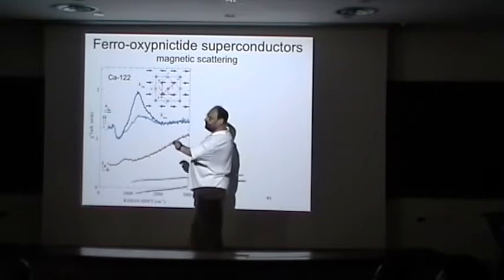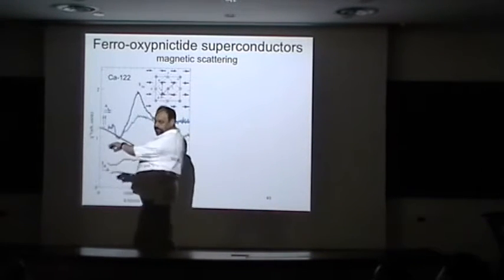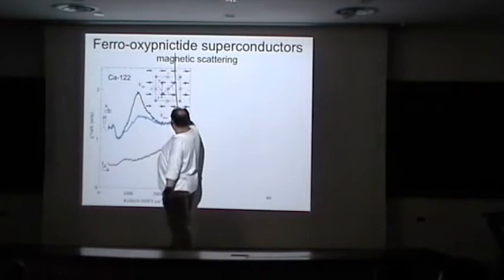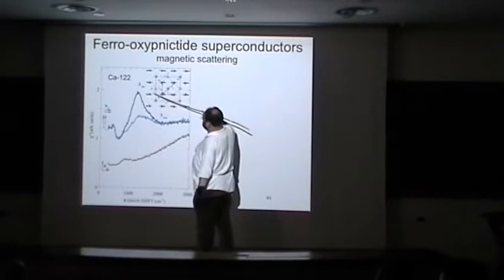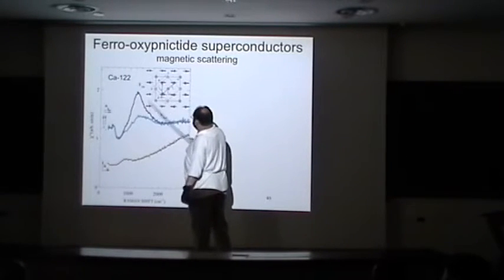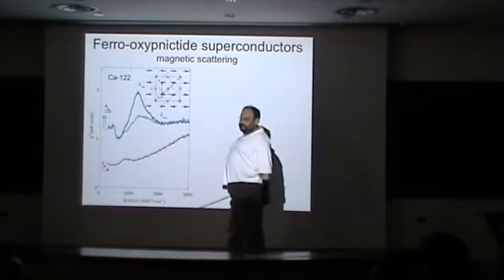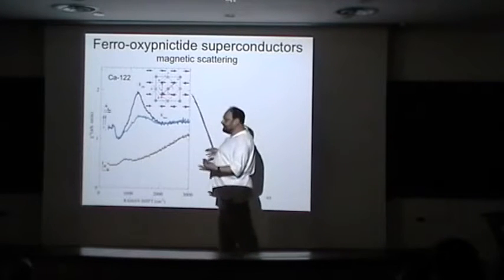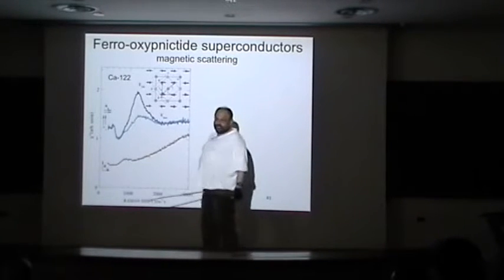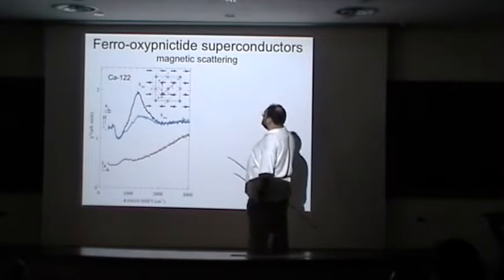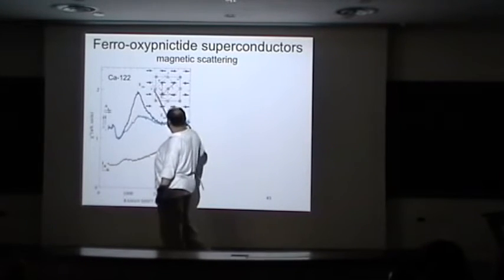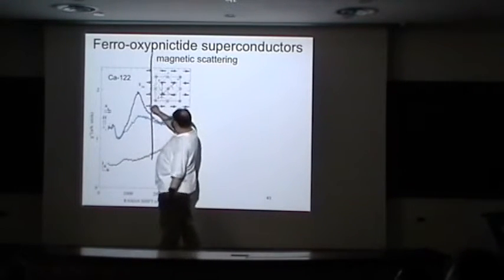So we are not flipping a spin like neutron scattering does. We exchange usually neighboring spins. And if it's a collinear stripe phase like the pnictides are, and we exchange these two spins, it will not cost us any energy, but if we exchange these two spins or these two spins, there is an energy price, and you see that in energy loss in spectroscopy, and by doing that, we can measure the cost. And what's neat about this is, again, playing with different symmetries, just the polarization of light relative to the crystallographic axis, because of this stripiness.